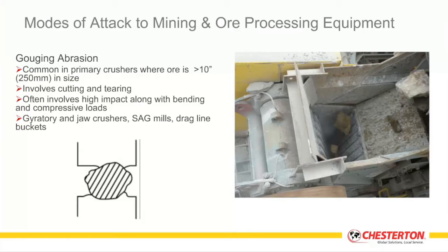This is common where your ore size is quite large, typically greater than 10-inch in size. It involves a cutting and tearing effect on the surface. Essentially, the ore is plowing a furrow through the base metal. And typically, this can also involve some high impact along with bending stresses as well as high compressive loads. The areas where you would see this commonly would be in your gyratory and jaw crushers. You may also see it in SAG mills, and again, as we said, in the dragline chutes, dragline buckets and front end loader buckets. This is a very high wear area.